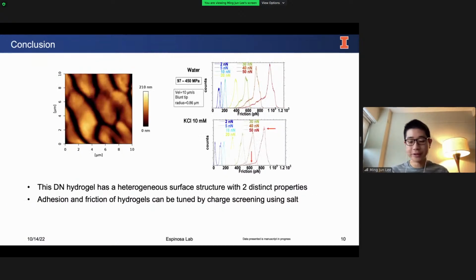To conclude my presentation, I want to remind you of two key components of this presentation. The first is that this particular system, agarose-poly acrylamide-co-acrylic acid, has a heterogeneous surface structure with two distinct phases of properties. And secondly, the adhesion and friction of hydrogels can be adjusted. We can control them by changing the concentration of the salt solution that we immerse them in over time.